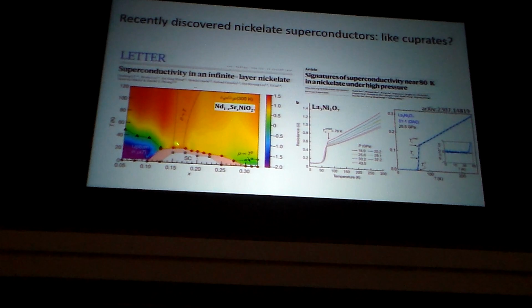Anyway, notice that in these so-called nickelates, the phase diagram, the TC as a function of doping, looks very much like the cuprates. There's this kind of dome of superconductivity. People who want to get papers into Nature now make all these beautiful colored slides that I have no idea what they mean. But I do know that at some doping, there is this normal state linear in T resistance, which is not understood in this material nor in the cuprates.